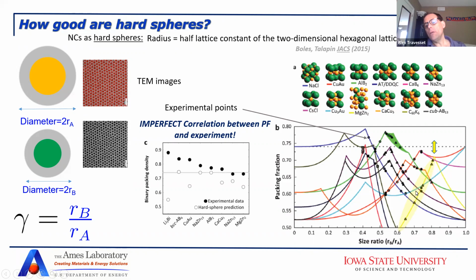In fact, Boles and Talapin have measured the packing fraction in the experiment, and you see that it is very far from what hard spheres predict. Here you have the hard sphere prediction, and here you have the packing fraction for the actual lattice, the experimentally measured one, and you see that there are big differences there. So the hard sphere model has some merits, but when you take it more seriously, it clearly fails to describe